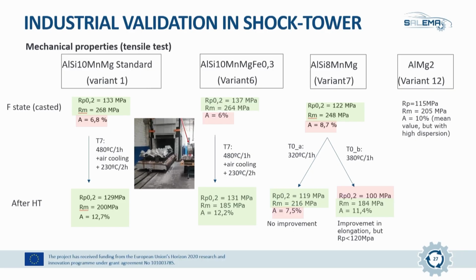And then for the aluminum magnesium 2, the main issue was that with this complex part, it was difficult to have it solidified within the die without cracking.